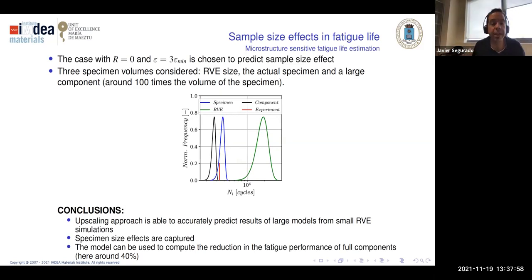So what we can see in the industry is that whenever we compute fatigue of a big component, we cannot use directly the results of the test. We have to do some derating. And this model allows us to know which factor we have to apply to go from the experiment to the real part, just based on Weibull or Gumbel theory of statistics, and it works pretty well.